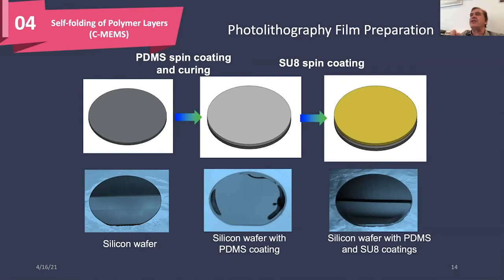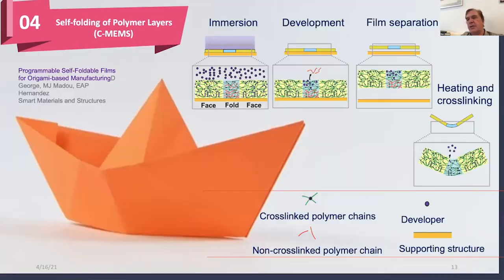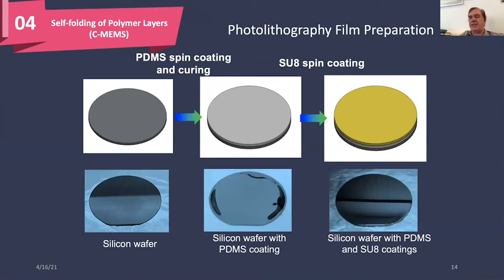And by the way, that is still an issue that we've recently also tackled. In this approach, you can imagine, because there's a substrate here, solvent cannot go this way. So that means we only will have folding upwards. We don't have folding downwards. Although this, we are currently also publishing, we found a way to have folds going this way and folds going the opposite direction. But in any event, at this stage, all we could do is have the films bent upwards by solvent evaporating upwards.